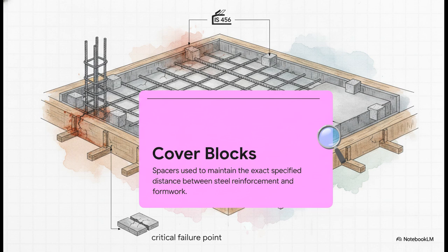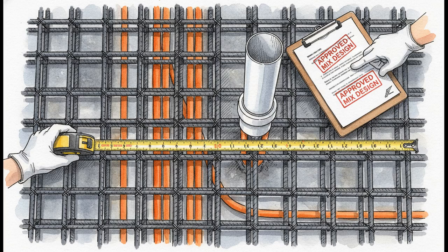I'm talking about cover blocks. Mandated by IS 456 Clause 26.4, these are mandatory spacers used to maintain the exact specified distance between the steel reinforcement and the formwork. If you ignore these, your steel gets pushed right up to the edge of the concrete, exposing it to air and moisture. And we all know what that means: rust, expansion, and eventually the concrete spalling and just falling apart. It is a critical failure point if you skip it. And this brilliantly illustrates how everything needs to come together before the pour.